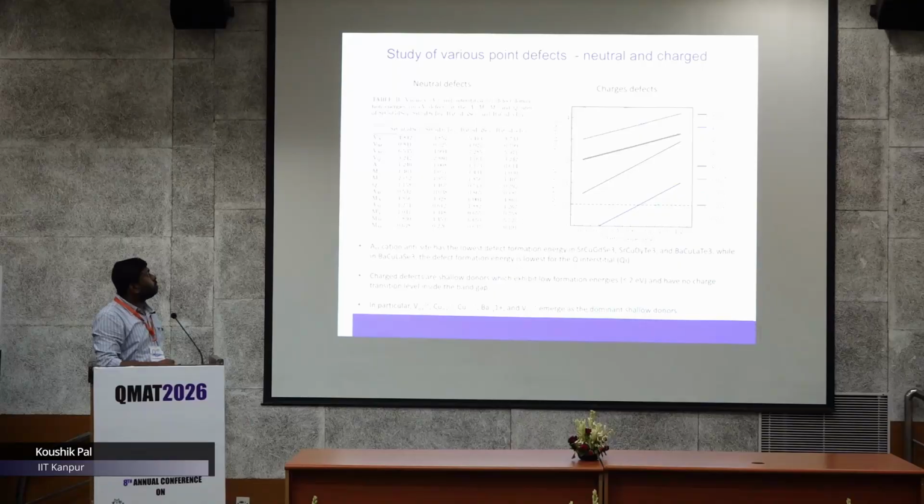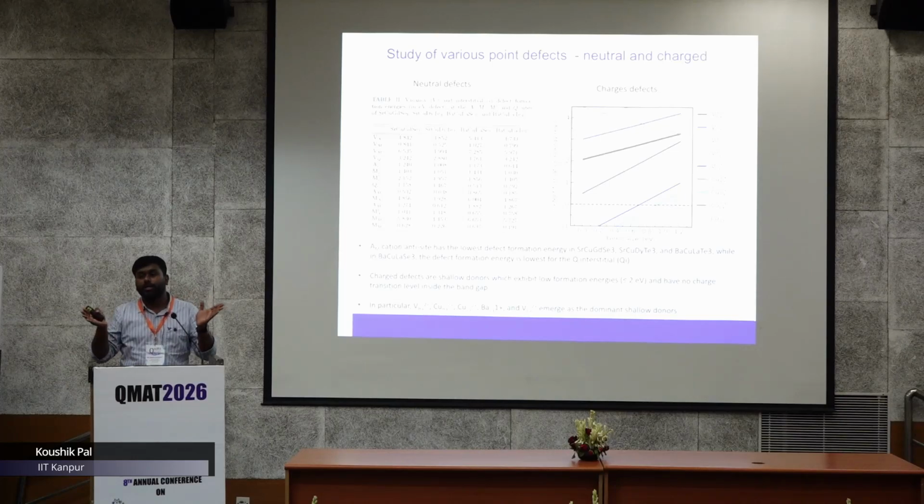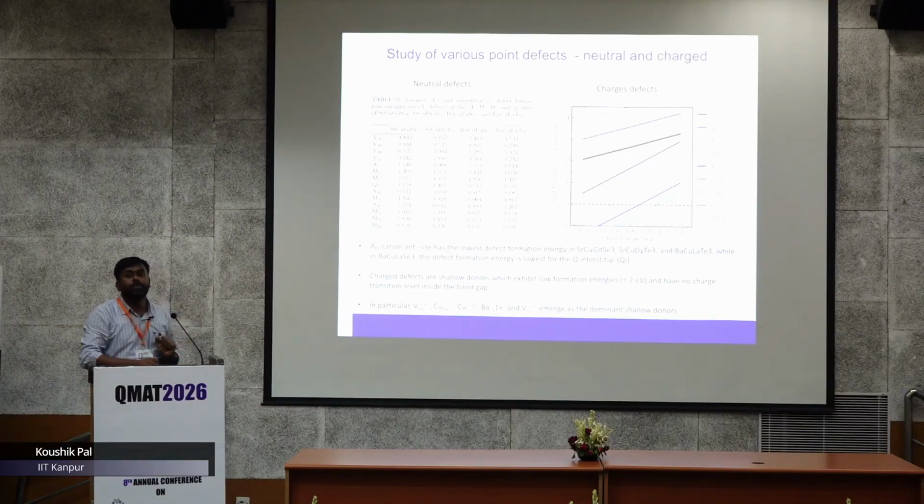And we have also performed defect analysis to see whether there would be any unwarranted defects within the band gap, because if there are unwarranted defects, they can trap the charge carriers, and then it can again deteriorate the efficiency. So here, from the charge defect calculations, we didn't find any defect states within the band gap. So there are no deep defect states, which is also good news for these compounds.